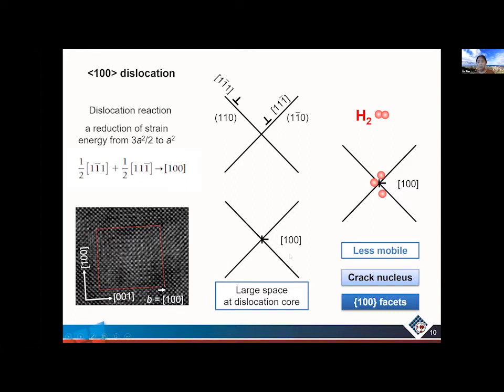Compared to the 111 type dislocation, the 100 dislocation has a larger space at the dislocation core, simply because it has a larger Burgers vector. And I suppose that if we have this larger space at the dislocation core of such a type of dislocation, it might attract the hydrogen atom. And with this hydrogen atom here, the dislocation might become less mobile, and with the strain accumulating, this site could lead to the nucleation of cracks, and eventually it will lead to the step-like crack with 100 facets.